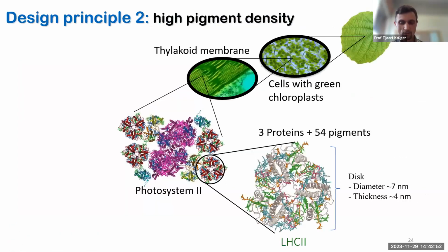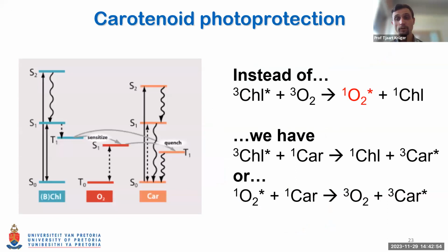Okay, so yeah, this principle has already been used to some extent in the literature, but very little. So in my opinion, a lot more effort can be made, especially in the context of dye-sensitized solar cells, where dyes are photosensitizer molecules that can undergo the same process as what I've explained here, and also organic solar cells, where the organic molecules also share the same properties. So once you have a triplet state there, it can interact with oxygen and be destructive to the solar cell.